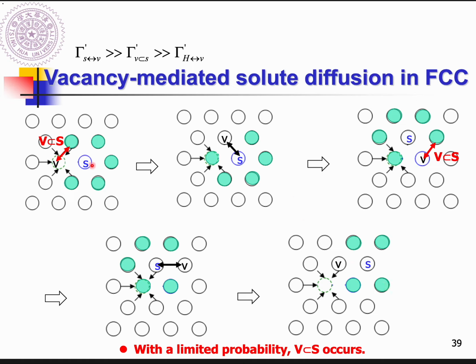The solute atom diffuses through this FCC structure. Based on this diffusion flow chart, you can observe that the solute and vacancy can be considered a pack or a pair. Packed together, they always bind together and move together due to this negative binding energy. And what allows this pack to move or diffuse from here to here? It is the jumping process between the host atom and the vacancy, enabling the solute to jump into the vacancy due to this gamma prime.